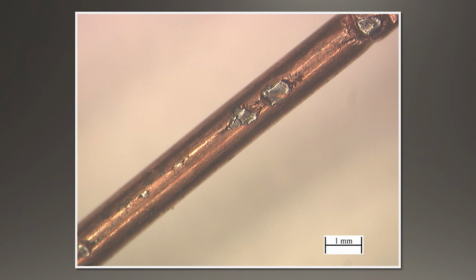Here's another example of a copper wire, but in this case, there's a whole bunch of inclusions. They're all magnetic, and it turns out this happens when a piece of steel accidentally got embedded in the molten metal being cast, and it broke up. It usually isn't there that long, so it doesn't dissolve completely, but it breaks up and gets involved into the cast bar and into the surface of the rod and into the wire. And this could be caused by something like an operator accidentally losing a tool and it falling into the molten bath.